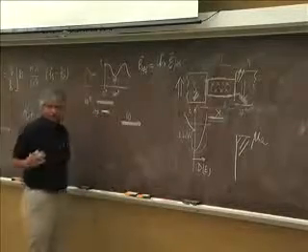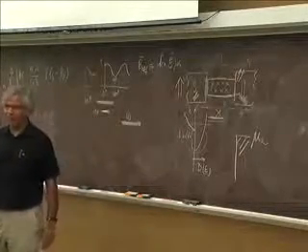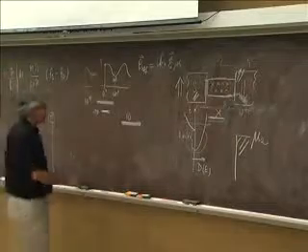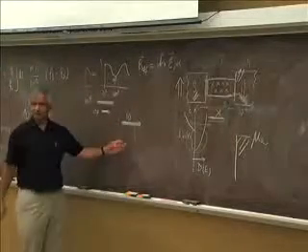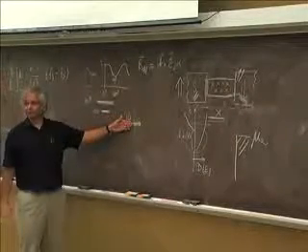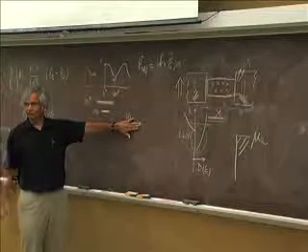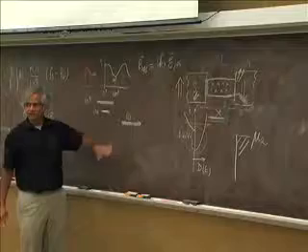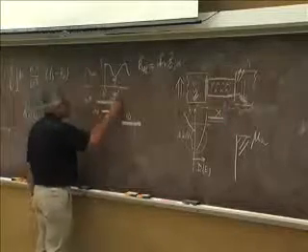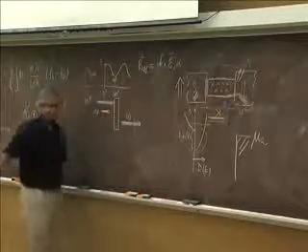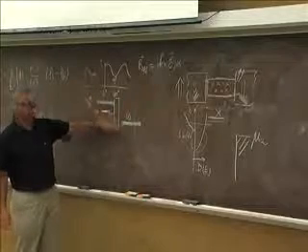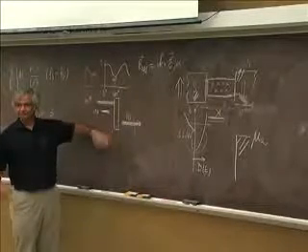And what you're really trying to do is inject more of one spin than the other. And the point is that if I look here, of course, it makes no difference because you're finally going to feed it into 10 lanes. So whether you have 100 or 10,000 doesn't matter. You keep them full anyway, no matter what. So the trick is then to put enough of a barrier here so that it gets harder for both of them to fill it.